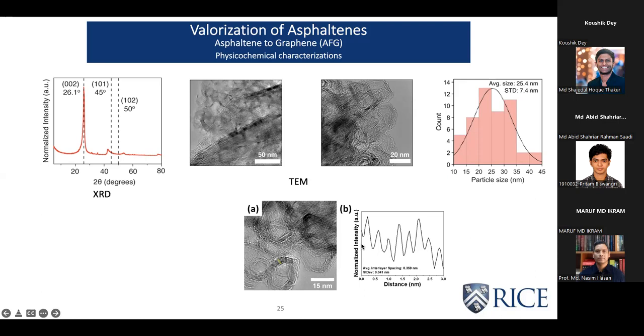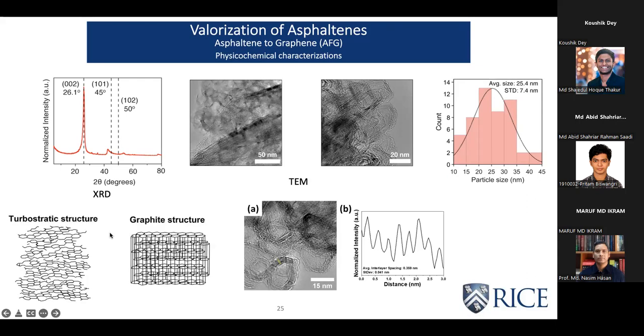From TEM, we also saw the interlayer spacing between the graphene sheets, which was found to be 0.359 nanometers, which is a little more than what is obtained in AB stacked or Bernal stacked graphene or graphite. So this gave us the idea that maybe the graphitic structure that we have is not a very pure form of graphite, and this is something in literature. Then we did some literature search and we found that what we are forming is not a well ordered graphitic structure. Rather, we have randomly oriented graphenes on top of each other, and these are called turbostratic graphite.